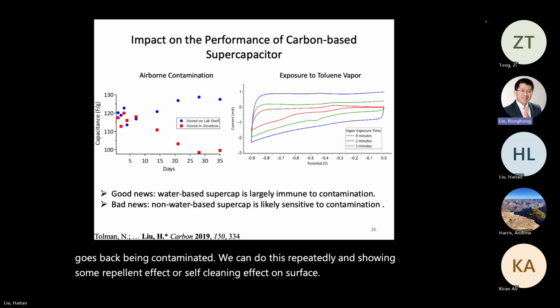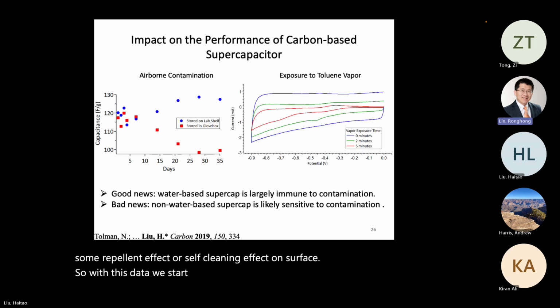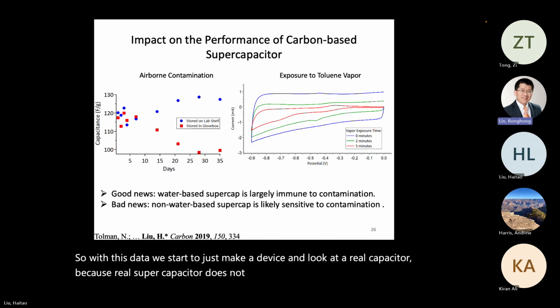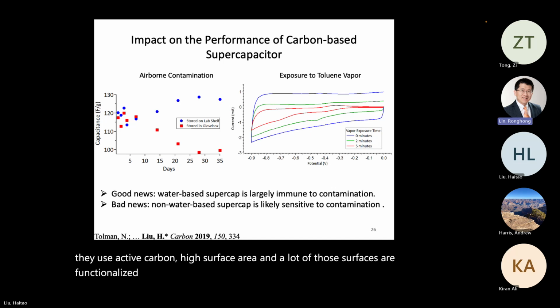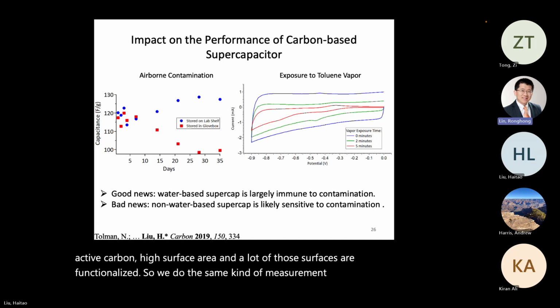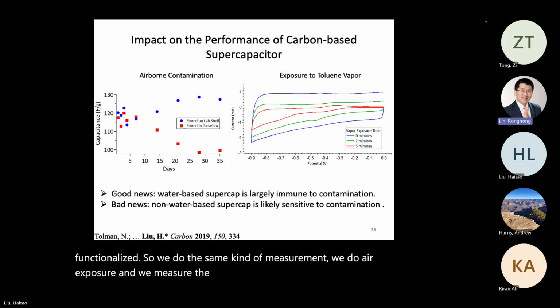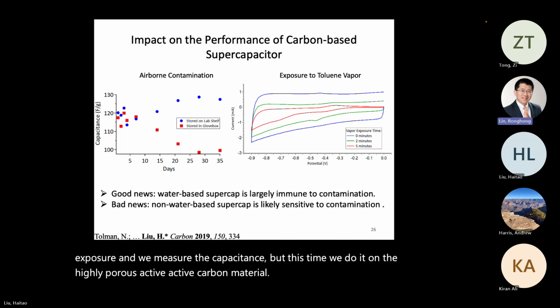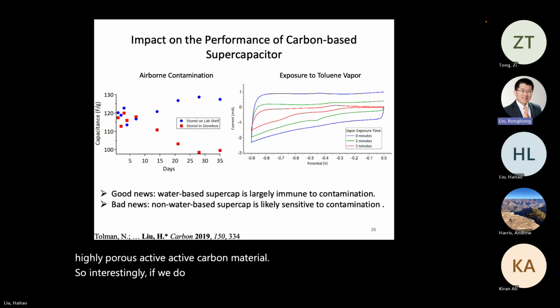So with this data, we start to make a device and look at a real capacitor, because a real supercapacitor does not use graphitic carbon. They use activated carbon with high surface area, and a lot of those surfaces are functionalized. So we do the same kind of measurement. We do air exposure, and we measure the capacitance, but this time we do it on the highly porous activated carbon material. So interestingly, if we do the exposure in air, there's actually not any downside.